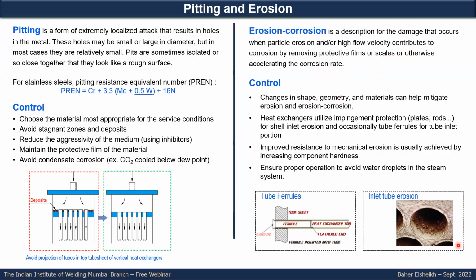Erosion corrosion: in this photo, you can see there is some high erosion to the face of the tube sheet, including the tube to tube sheet joint and the inlet or first part of the tube itself. So by the time this might have corrosion or metal loss leading to a leak here. So you might think about changing the geometry configuration to avoid such high impact of the erosion, or maybe utilizing impingement protection in the channel itself, some perforation or something like that, to protect the tube from direct impingement, or improve the resistance of the material by using higher hardness material. And in some designs you can have ferrules here to protect the first part of the tube, including this flared end, which will protect the joint as well.